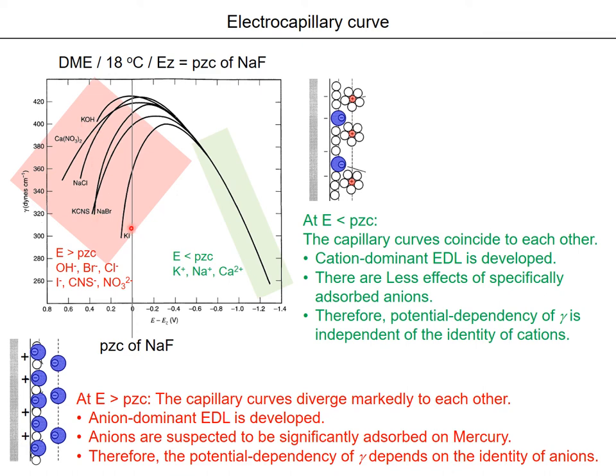All of the curves look like the normal electrocapillary curve expected from the previous slides. Around the point of zero charge, for each respective electrolyte, you should have the maximum value of the surface tension. However, far from the point of zero charge, the surface tension goes down, sometimes in the negative direction, sometimes in the positive direction. For KI, sodium bromide, KCNS, sodium chloride, or something like that.